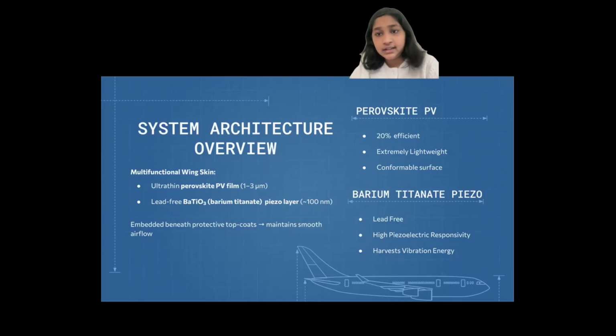For the photovoltaic layer, I chose ultra thin perovskite films because they strike a rare balance between high power to weight ratio, flexibility, and aerodynamic friendliness. At just 1 to 3 micrometers, these films are roughly 50 times thinner than a human hair, which allows them to conform flawlessly to the wing surface without disrupting airflow. Their low thickness minimizes changes in surface roughness, which is a critical factor because even subtle roughness can prematurely trigger turbulence.